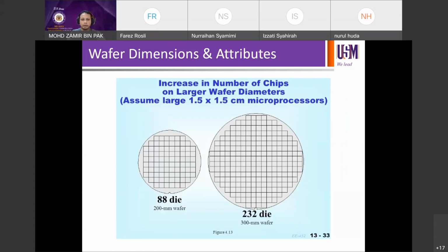For example, if you run 200 mm 8-inch versus 300 mm, and well, this is considered the old school version of the die size, because it doesn't have many, so only 88 and 232. So if you use the same area of a chip, for example, on 200, say you can fit 88 dies, and then if you run the very same chip dimension on 300, then that will fit up to 232. It's the very same chip, but you just upgrade the size from 8-inch to 12-inch. So that's the difference in the number that you can get on the very same wafer.